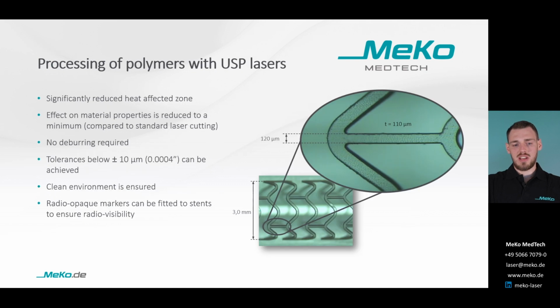Now let's have a look at some examples from the practice. The picture shows a laser cut scaffold. The material here is Zeus Absorv XSE. The strut width of the horizontal connector is 120 microns and the material thickness was about 110 microns with an outer diameter of 3 millimeters. The scaffold design used here is a very simple generic one, which is used for testing purposes only. The scaffold shown was laser cut only.